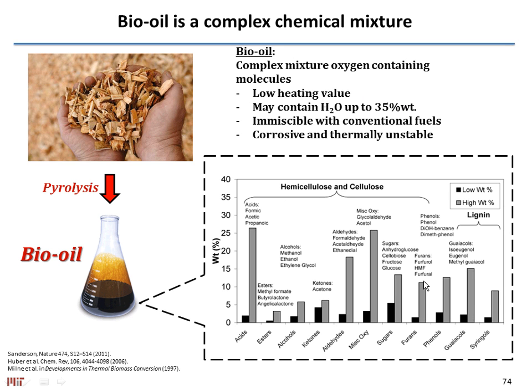But just to give you an idea of bio-oil, right? So you have your wood chips, for example, here. You pyrolyze them through these very simple, downflow or upflow reactors. You liquefy it, you get this bio-oil, and what you have is this family of components, right? You have short oxygenates, you have furanics, phenolics, and a whole bunch of different materials over here. You have a lot of water still in there, and you have a lot of organic acids that are corrosive. So that's why you cannot keep bio-oil for a long time, because it just starts polymerizing. So one of the big challenges is, how do you stabilize it? How do you do this first deoxygenation step so that you can do something useful with this bio-oil.